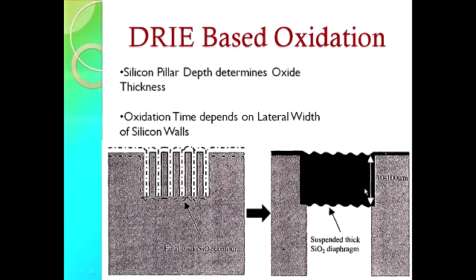Oh, I see. So basically you etch not the oxide but the silicon, and then you oxidize the membrane. Is that right? No, we don't oxidize the membrane. This membrane is the oxidized portion of this. I see. So the dark portion shows the oxidized part, and this gray portion shows the silicon wafer, which we can etch to isolate it.